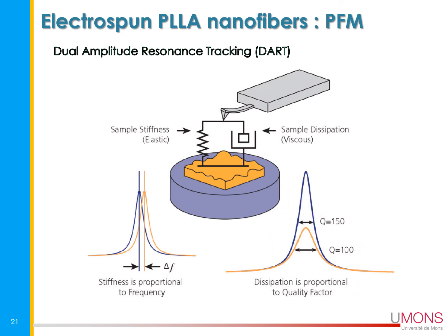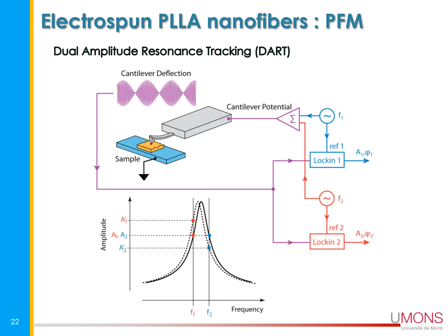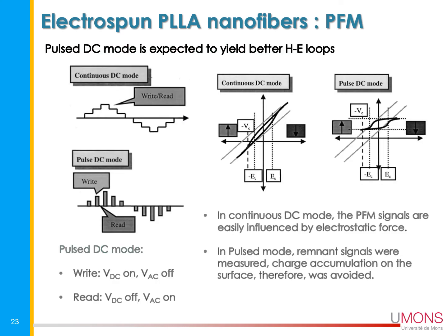So we have this situation, and one way to estimate and to track the frequency shift amplitude is to use this dual amplitude resonance tracking. In fact, we are applying two signals, and the idea is to nullify the difference between A1 and A2. Be sure that we have the frequency always in the middle of frequency 1 and frequency 2. This is a trick that most of us are using to be sure to measure this frequency.